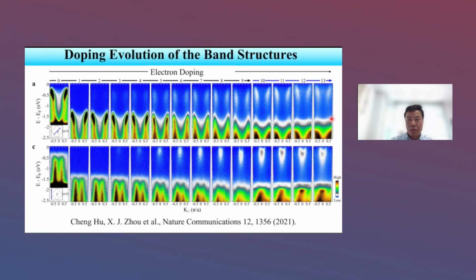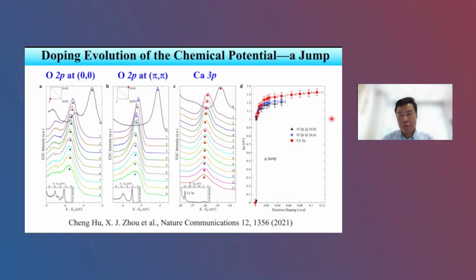Okay. So basically, from this experiment, we can also measure the chemical potential shift with the doping. So here, by using some core level, like calcium 3p or oxygen 2p, by using core level, we can measure the chemical potential change with doping. So we can really see that at the beginning, when you dope the system only slightly, a little bit of electrons, you already see the chemical potential jump by 1 eV. Then it keeps increasing slowly, gradually, with further increase of electron doping. So this is the jump. Altogether, it has about 1.3 eV chemical potential change here.